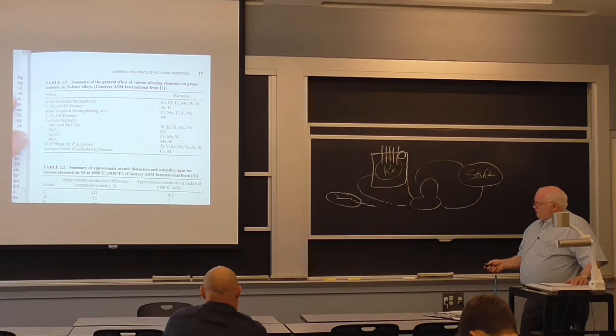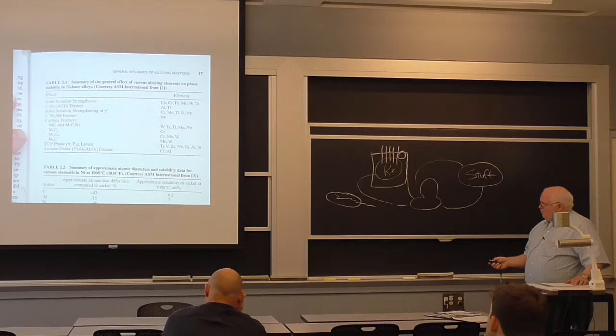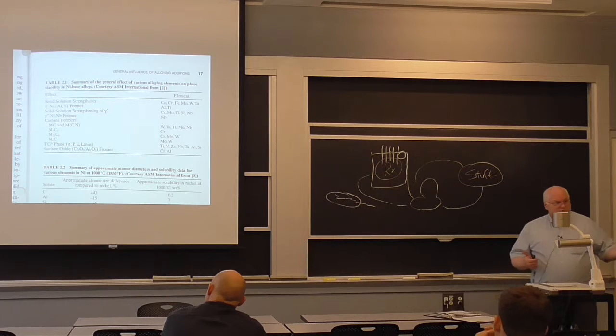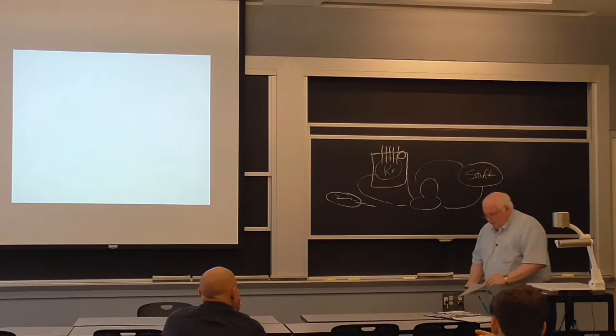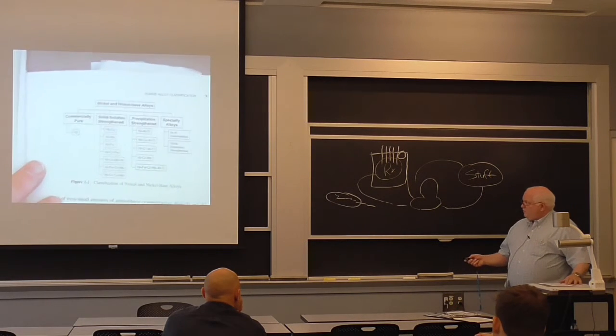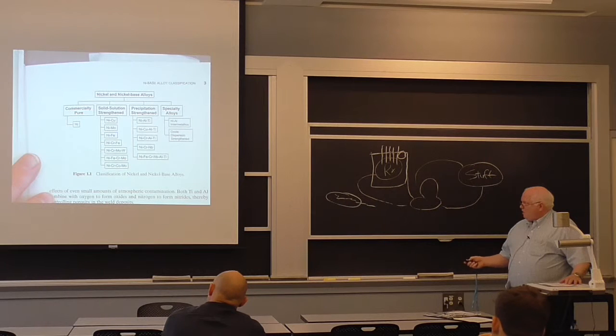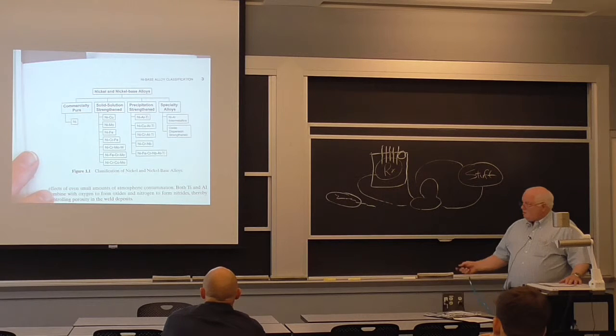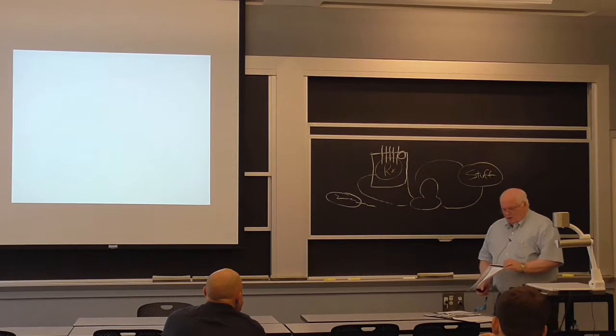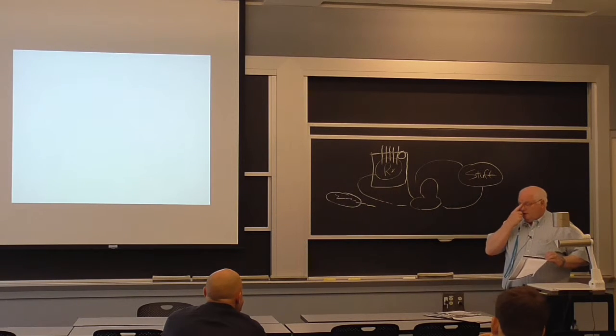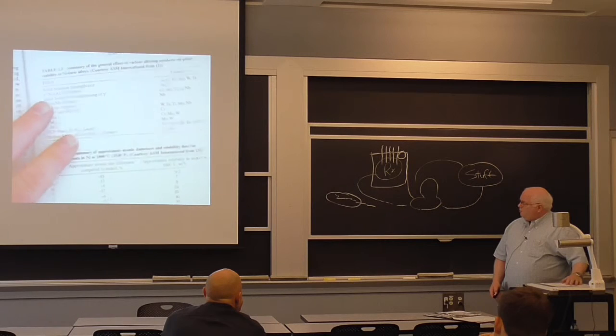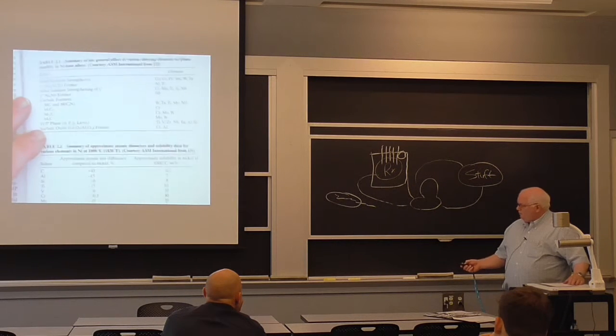Some of these can be very brittle in stainless steel. The sigma phase can embrittle the steel. And then we put chromium and aluminum. Those are the two things that give you good high temperature strength. So if we go back to our alloys, the nickel alloys are used for corrosion resistance, primarily solid solution, and high temperature strength in very high temperature. I mean, these are our workhorse materials for very high temperature processes where we're getting above the stainless steel, which is, let's say, 600 degrees C is about as high as you want to go with stainless steel. And you can get up to 1,000 C with some of these things, maybe even 1,100 in some cases.